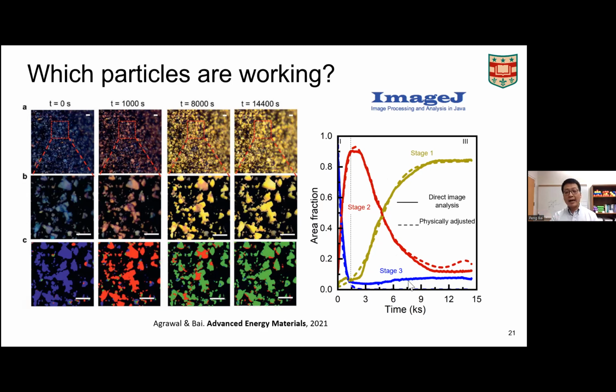So this kind of areal evolution curve shows that there is indeed a sequential reaction process, right? It's not like everywhere is progressing at the same time, and all of a sudden it goes to full. And more importantly, we were able to demonstrate.